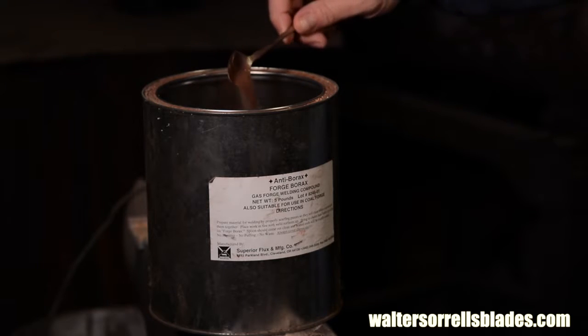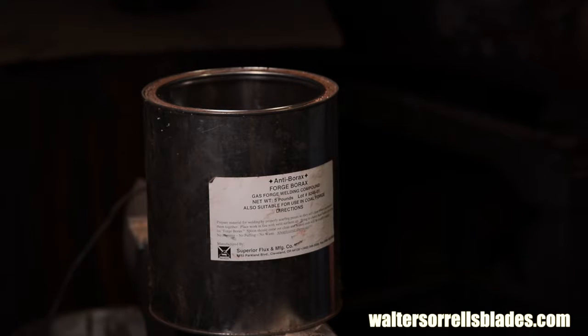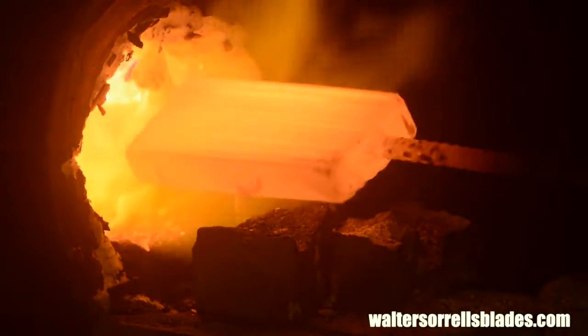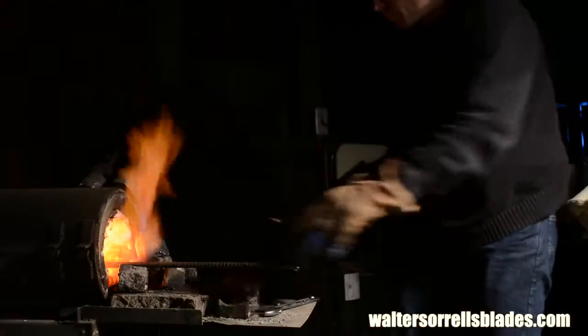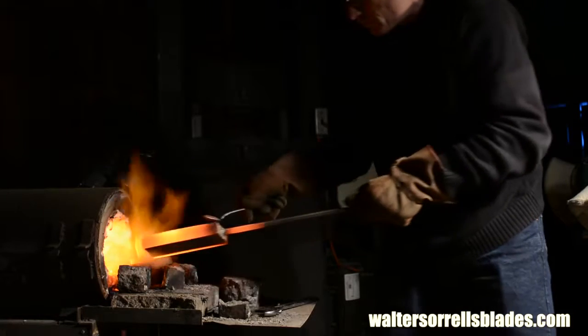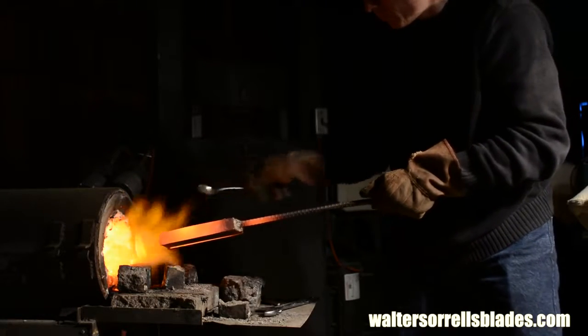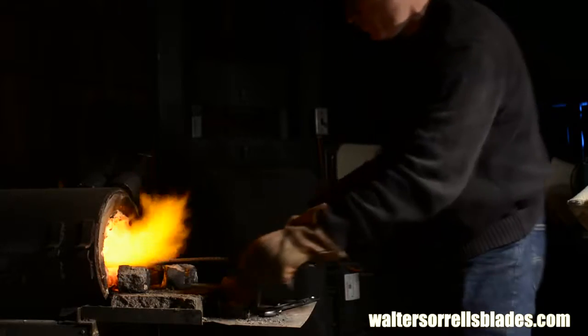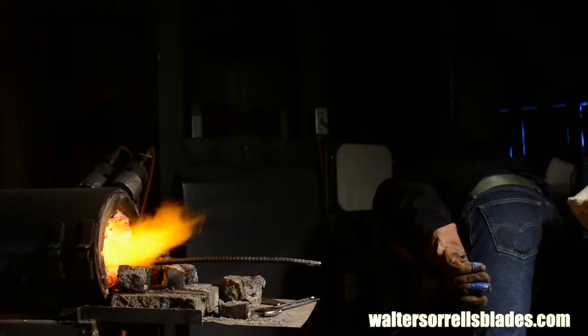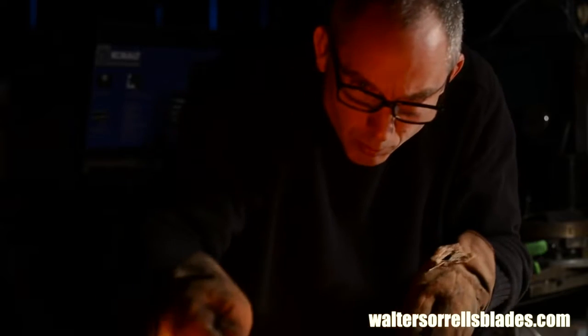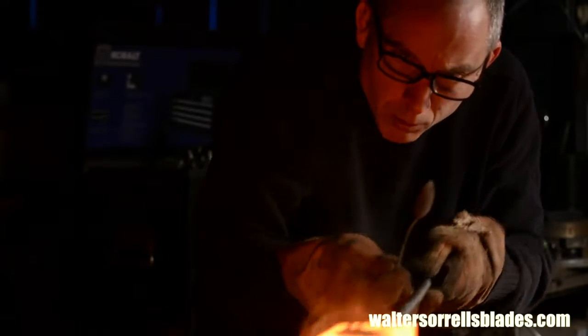That water turns to steam once it goes into the forge, causing the borax to sort of blossom up off the steel, and often it falls off or blows off, so it's a little trickier to use. But still, grocery store borax works just fine. So, I heat the billet until it starts to glow a little, then I'll pull it out and sprinkle it lightly with flux. If you try to put the borax on before the steel's hot, it won't stick to the steel and it'll just blow off into the floor of your forge. But don't wait too long or you'll get scale buildup that could contaminate things later.